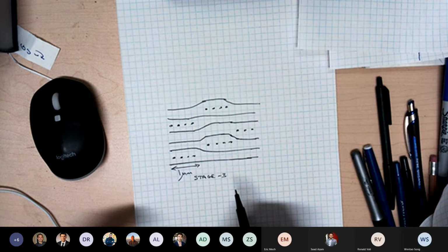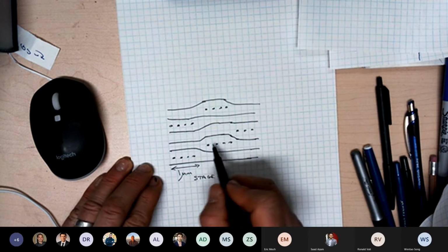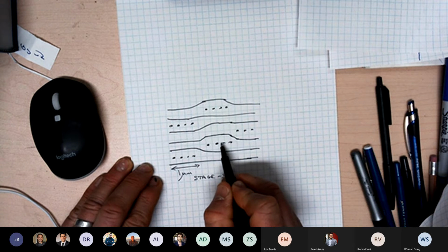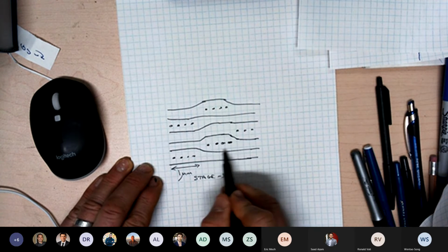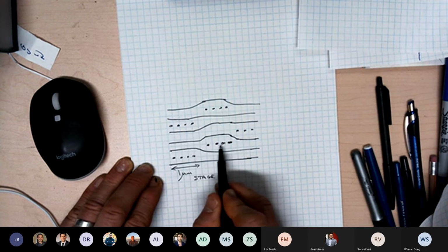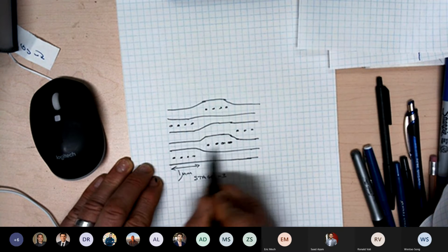And why do they form? Well, once you have 1 lithium atom that expands the layers, it's easier to put the next ones nearby. So there's an attractive interaction between the lithium atoms within a layer. But, like Eric mentioned, there's a repulsive interaction between lithium atoms that are above one another. So these islands try to separate from one another.